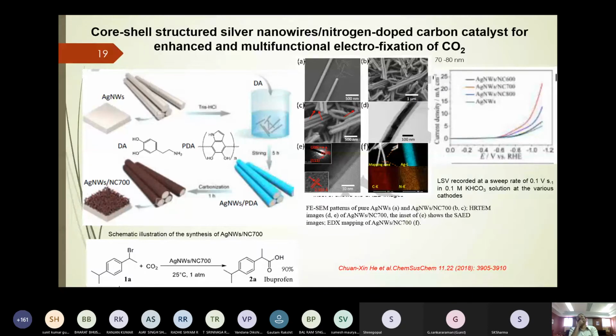Actually, now I show SEM, FESEM plus TEM, HRTEM, high resolution transmission electron microscope. It shows a tube-like structure of silver nanowire. See here, if you go for SEM, there we can see colored things also. This shows that we get a very small size of 10 nanometer of silver nanowire on this nitrogen doped carbon. Then we have tested how it works. There we can see from the cyclic voltammetry this silver nanowire NC, for example, obtained at different temperatures, 600, 700, 800.